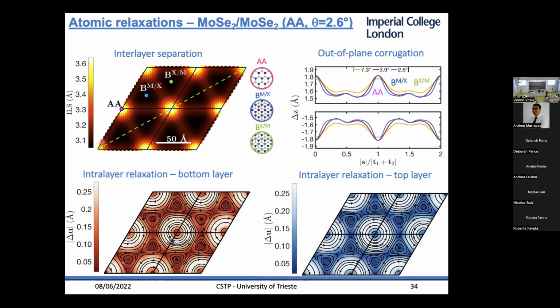And so basically what you see is you have AA regions in the corner, and then you have Bernal of one kind, Bernal of another kind, with a little bump in the middle, and then AA again, right? The out-of-plane corrugation follows the stacking of the registry. In plane, we have these kind of vortices, rotations around the AA regions, because the system wants to minimize this unfavorable stacking. So if you are in the AA and you start rotating a little bit, you enlarge the Bernal kind of stacking and reduce the AA stacking. So the system doesn't want to be in this AA. And so you have this rotation clockwise on the top layer, for example, and counterclockwise on the other layer.